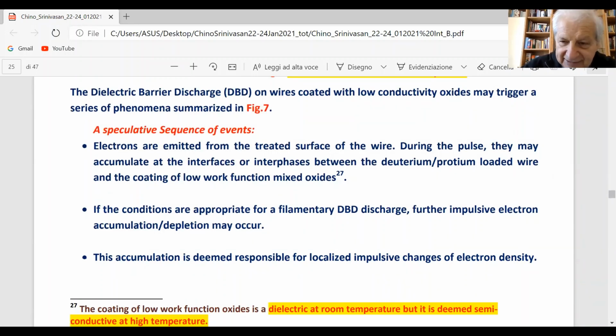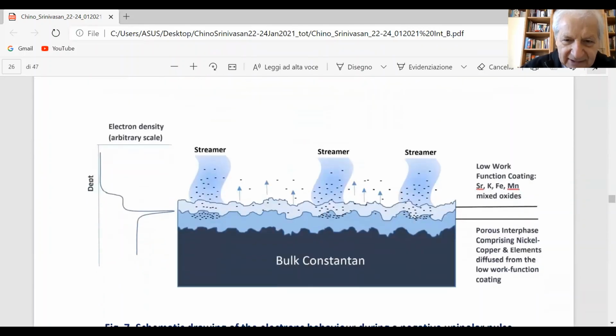The speculative sequence of events here is that the electrons are emitted from the surface, and at the proper time, when they are at maximum intensity, they interact with ionized hydrogen or deuterium. This is a sketch, a possible model of what happens. We have the constantan wire, with the surface covered with low work function materials, which means electrons can go, and they are accelerated by the high voltage, and these electrons cross with hydrogen, ionized hydrogen.